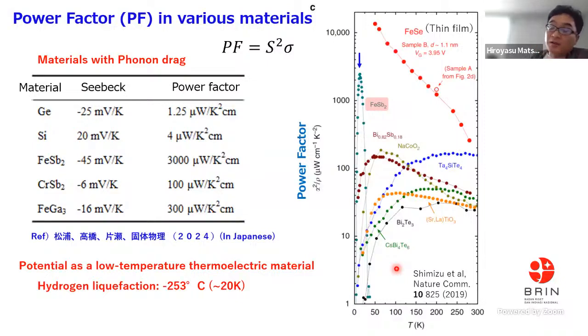The important point of phonon drag is that they have large power factors. For example, iron antimony 2 has a very large power factor, 3000 microwatt per centimeter Kelvin squared. This is the temperature dependence of power factors. So these materials are potential materials for some electric devices. Iron antimony 2 is located here. The power factor is very, very large compared with the other materials. Therefore, phonon drag is focused on for some devices, especially in the low temperature region.